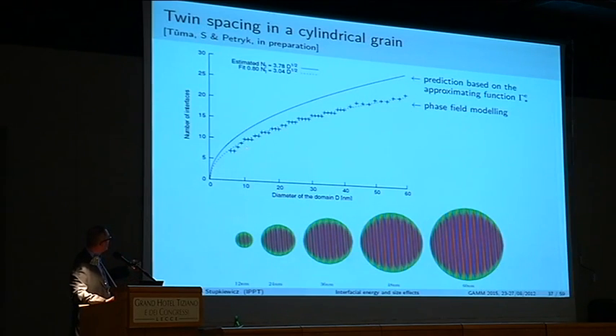So this is a 2D grain. And this is the result of this simplified model that I showed before, that we could do by minimizing the interfacial energy with respect to the twin spacing. And you have here this square root dependence. This is actually number of interfaces, but this is exactly the same as that square root dependence one can easily show. And this here is the result of phase field modeling.